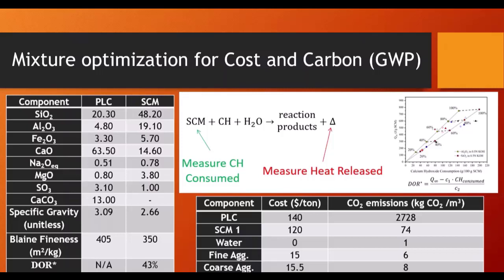How do we get that reactivity? We get it through science. We know that a pozzolan has to react with calcium hydroxide to be efficient. So we say, how much of the pozzolan has reacted with calcium hydroxide in a pore solution? And in doing that, how much of the calcium hydroxide has been consumed and how much heat has been generated? And once we do that, we can compare that to a scientific equation that can be written that says, when this reaction occurs, this is how much heat is given off, and this is how much calcium hydroxide is consumed, and therefore this is the percentage of your material that is reacting.